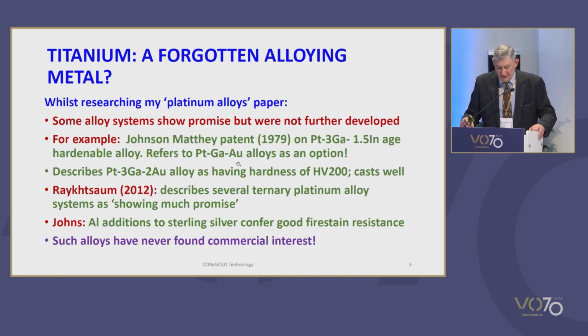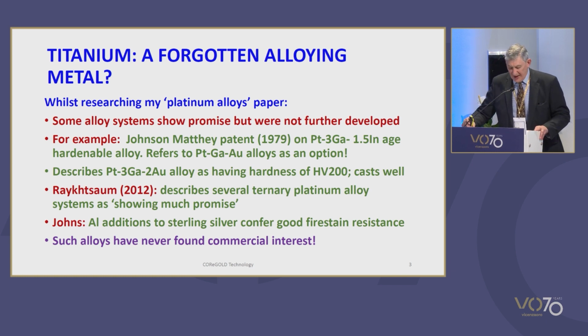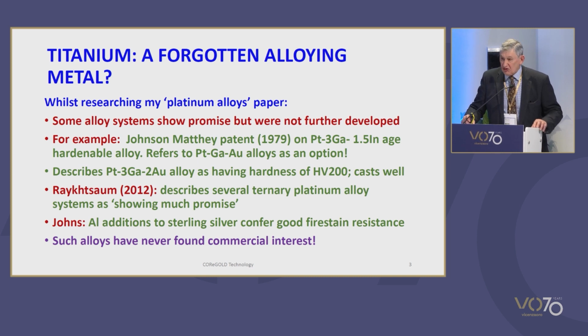It was while researching my recent review of platinum jewellery alloys that I became aware of alloy systems that showed much promise, but were never further developed to commercial application for jewellery. An example of this is described in a Johnson Matthey patent for the age-hardenable platinum gallium indium alloy, platinum 3 gallium 1.5 indium. In this patent, the inventors also refer to platinum gallium gold alloys as an option, with the use of yttrium additions of about 0.1% as a deoxidizer. The platinum 3 gallium 2 gold alloy is claimed to have a high hardness of 200 Vickers. Such gold alloys are said to cast well.